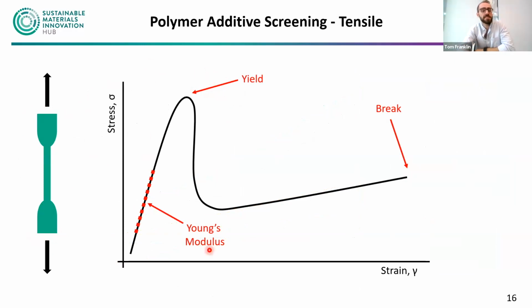So the Young's modulus down here is this linear portion, which is largely the recoverable deformation. If you think of a plastic bag, if you were to just gently pull it apart and then release it, it would maintain its original dimensions. If you were to keep pulling it, it might be quite hard at first, and there comes a point when it becomes quite easy and you can really stretch it out. That is the yield. So when that polymer yields, that deformation is irreversible. You've changed the dimensions of it. And if you keep pulling, ultimately, that plastic bag or that polymer sample will break. I'm going to focus on the yield and the Young's modulus.